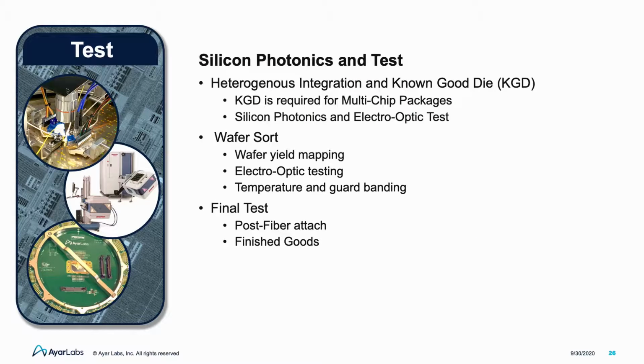In closing, KGD is a requirement for successful MCP integration. And to achieve that, we need electro-optic wafer sort that ideally supports 300 plus probe pins, up to 24 precision aligned fibers, roughly plus or minus 1 micron, and all running at 100 degrees C or more. And finally, final tests must be adapted to allow for post-fiber attached testing, ensuring that parts meet specifications before reaching finished goods.